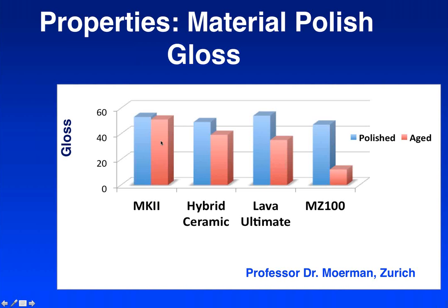Looked at the change in gloss after aging, so Mark II got a little less glossy. Hybrid ceramic lost a little bit more gloss than the Mark II, but was higher in gloss retention than the Lava Ultimate, and all of these materials were much, much higher than the gloss retention in MZ100. So again, we're kind of in between a ceramic and a composite resin.